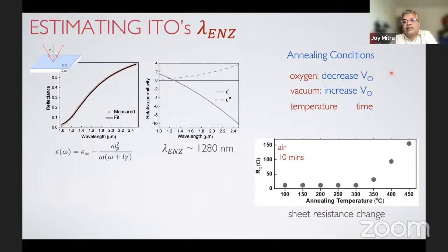We went ahead and started annealing the system under various conditions. What are the annealing conditions? The annealing conditions were either in oxygen-rich atmosphere or oxygen-lean atmosphere, with temperature and time as parameters. Okay, so we obviously have to estimate the lambda ENZ, which we mostly did from angle and wavelength dependent reflectivity measurements. A typical measurement is shown here, from which we back calculate the relative permittivity for the ITO coated glass stack. So we take the experimental data, fit it, and then calculate the relative permittivity. And for this sample, as you can see, the epsilon goes to 0 at around 1280 nanometers.